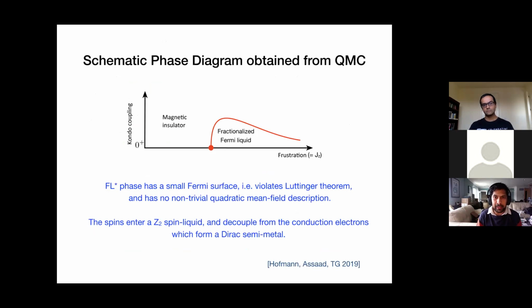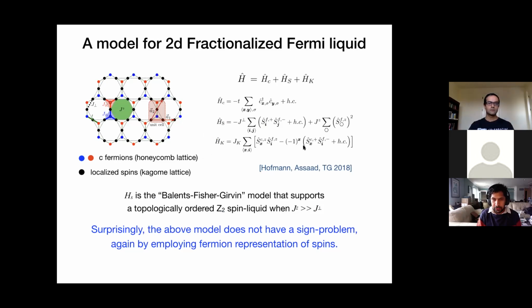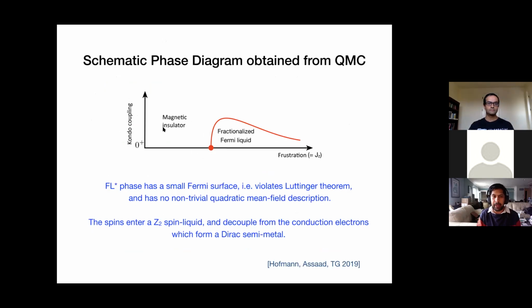So schematically you get this phase, you get a fractionalized Fermi liquid, and you get a magnetic insulator. Because of this funny coupling, you don't really get a conventional heavy Fermi liquid. You get a magnetic insulator. Anyway, the main point is this fractionalized Fermi liquid has a small Fermi surface. If you just write a symmetric state, which is a heavy Fermi liquid, that doesn't break any symmetry, it will have a large Fermi surface. In our case, this phase has a small Fermi surface of Fermi volume 0. It's just a Dirac fermion, which is inconsistent with Luttinger theorem.